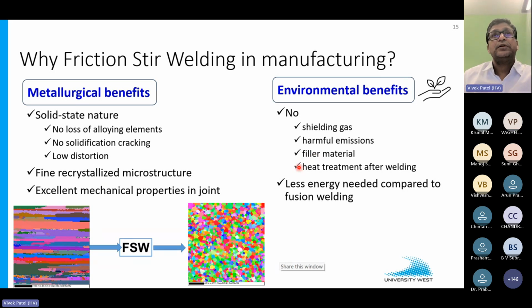And if you have the right process parameters and right tooling, then you can eliminate the heat treatment after the welding. So you can have the weld nugget almost similar to the parent material. So you don't need a heat treatment, and here also you save a lot of resources. So we call this process quite sustainable, and that's why a huge demand is coming from automotive companies for different applications. And also in terms of power, friction stir welding consumes very, very less power compared to fusion welding. On average, maybe 50 to 70% less power is used by friction stir welding when we compare with TIG or MIG welding.